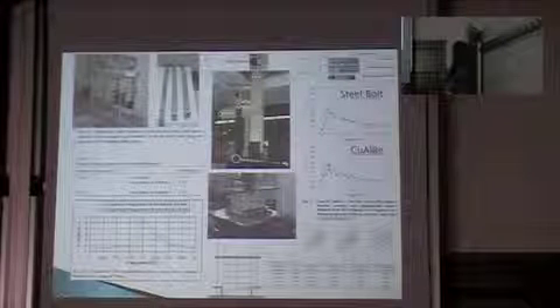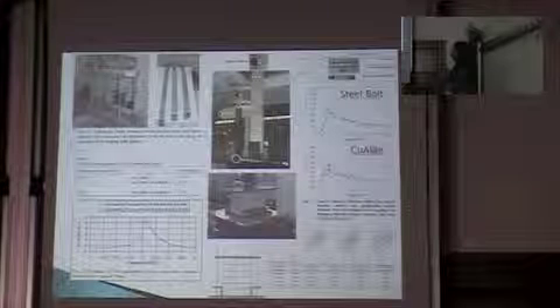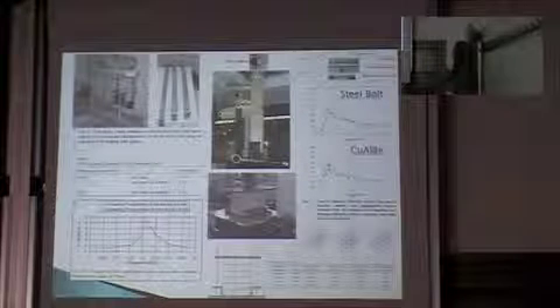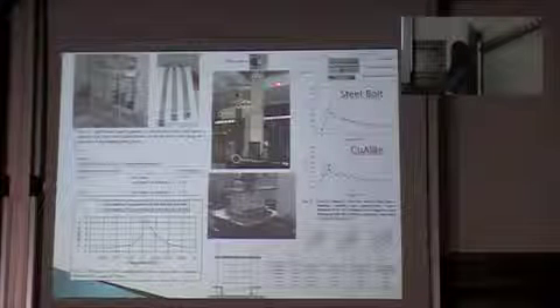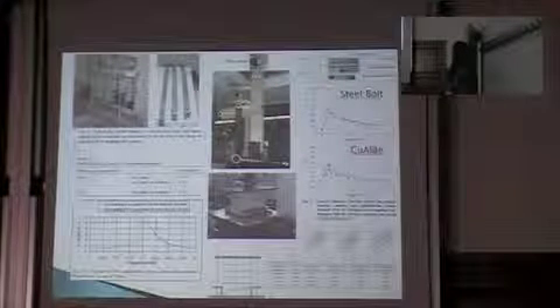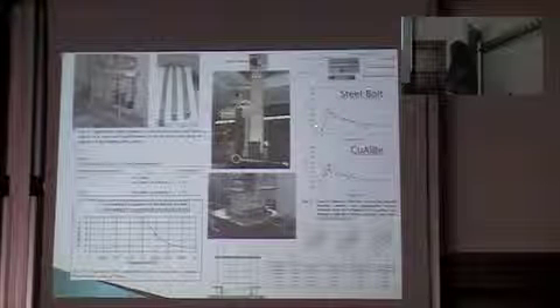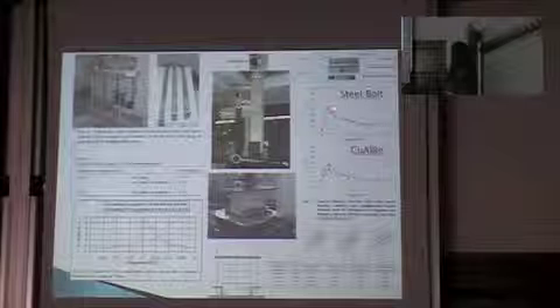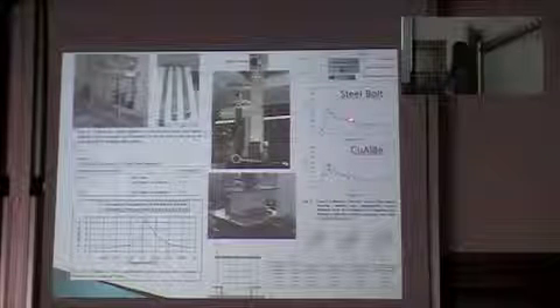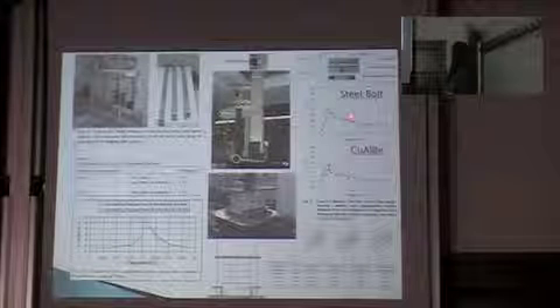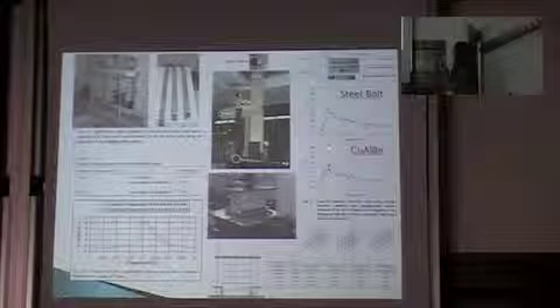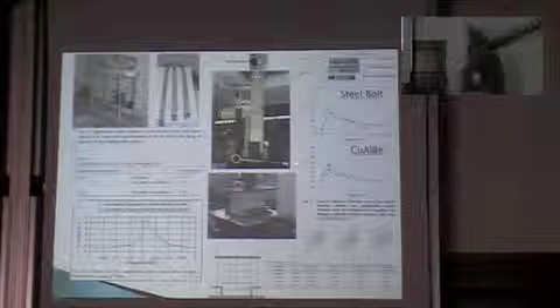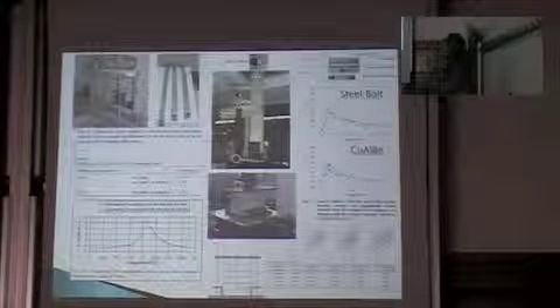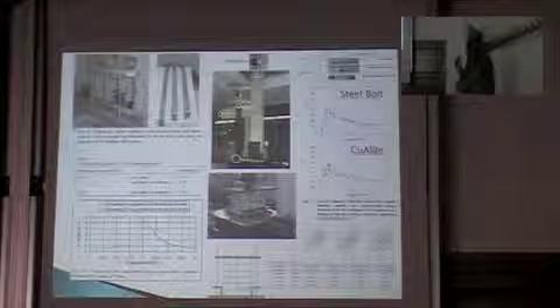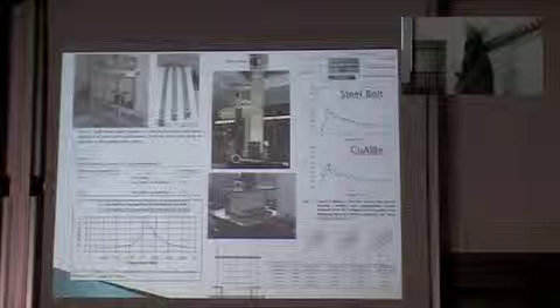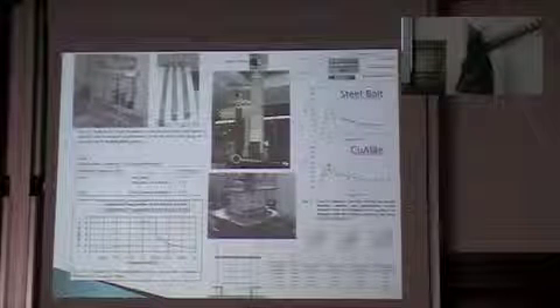And we repeated it using both steel bolts and shape memory alloy bolts. And we compare the results: with steel bolts, the frequency in the forward and backward tests is the same, whereas you can see a clear shift when you introduce the impact bolt in shape memory alloy. And the studies also need to take into account the impacts between the hosting hole and the shape memory alloy device itself.